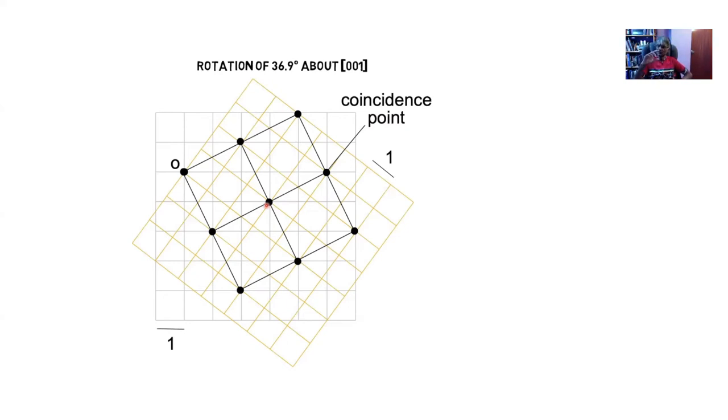So the volume of the black cell here is √5 times √5 times 1, which is 5. Whereas the volume of the primitive cubic lattice is just 1. So the CSL cell has a volume which is 5 times bigger than the primitive cubic cell. And that's because a fifth of the lattice points in either one of the yellow or the gray cells, a fifth of the lattice points share exactly the same position in space, okay?